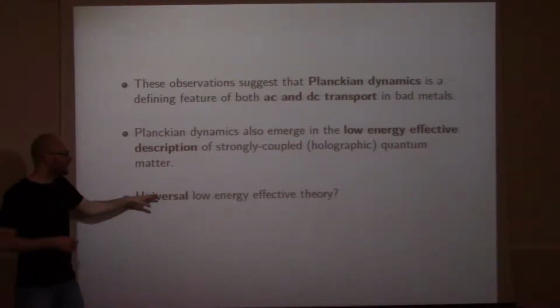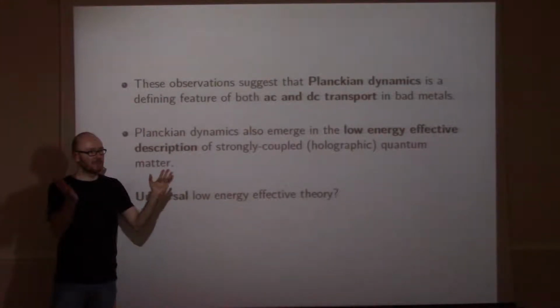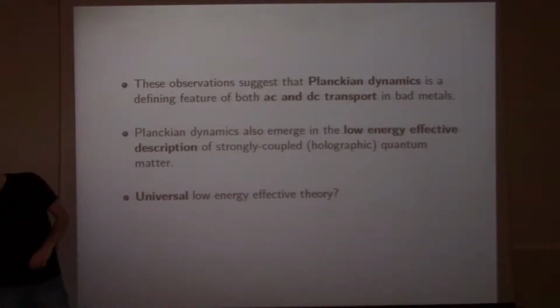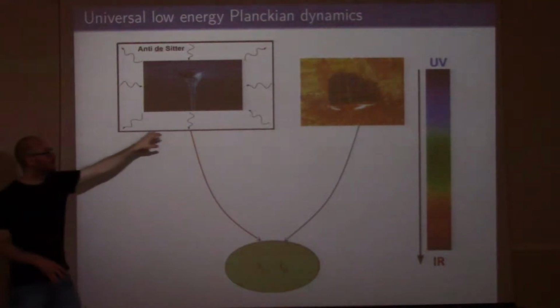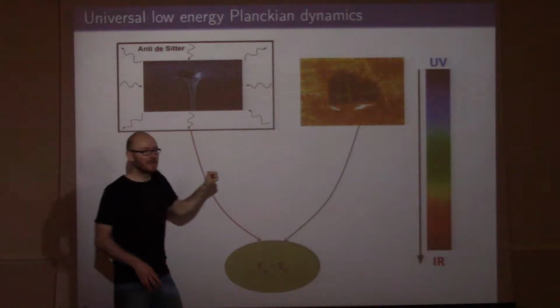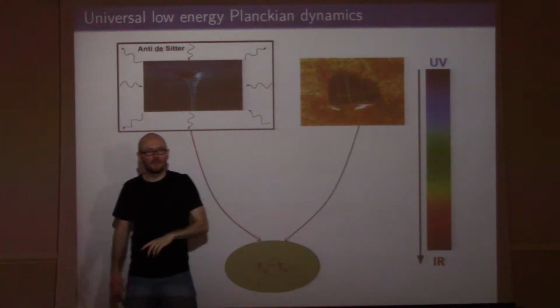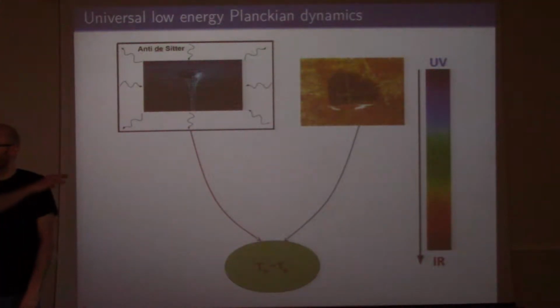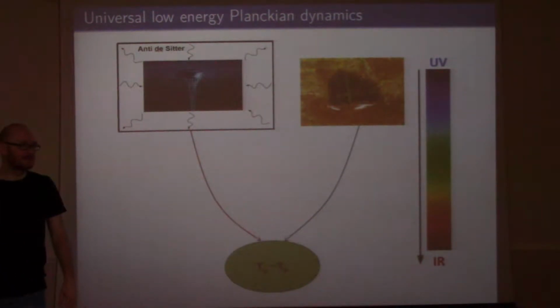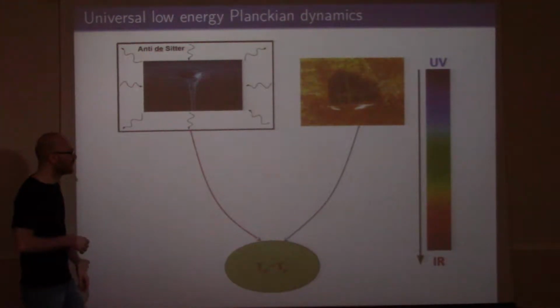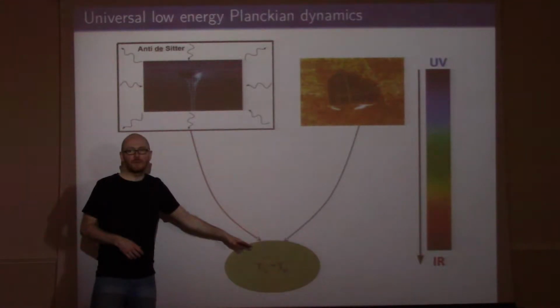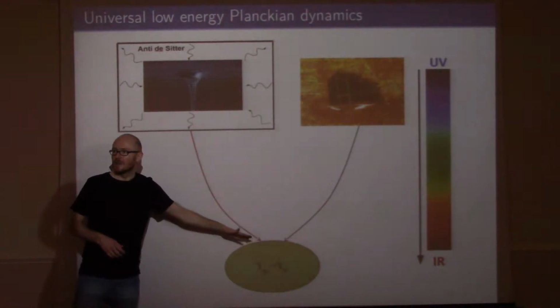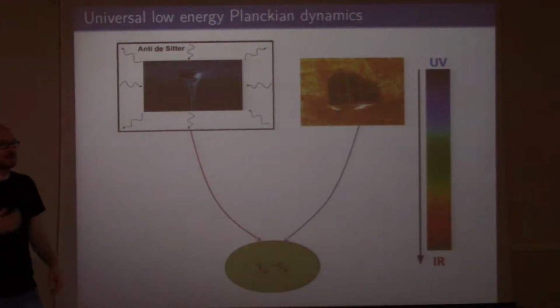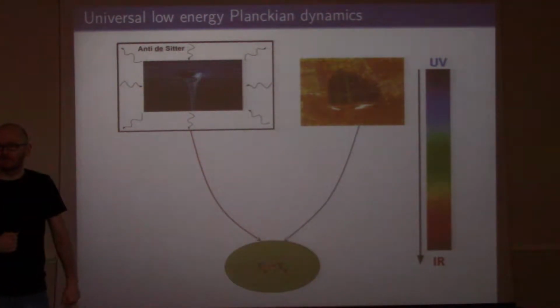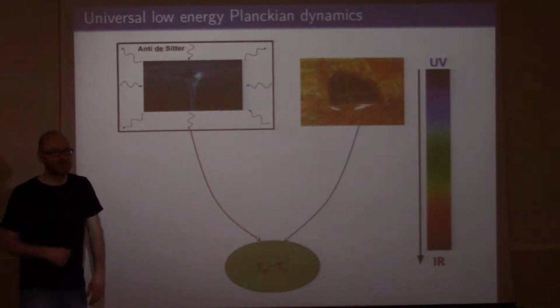So what it suggests is that there's some sort of universal low energy effective theory that would describe both of these systems. To put it a little bit more pictorially, we have these two very different systems. Here's a black hole in AdS. There's some crystal of a high TC superconductor, and they're very different on macroscopic scales, so we shouldn't try matching the UV theories. At least from my point of view, I don't think this is necessarily the best thing to do. But certainly it seems that the IR effective description at low energies shares a number of features. So it gives you some hope that you can understand something about one system by studying the other system at long wavelengths, very much in some RG flow spirit.